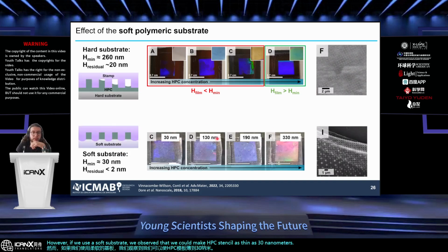And the reason that we believe this is possible is that with a soft substrate, I could press into the substrate and basically force the HPC to fill the stamp evenly. Another important benefit of this is that we would not have so much residual layer that we have to etch in the second step. So we only perform a 30-second UV ozone cleaning step, which is really making our life much easier, and we can avoid any kind of clean room steps. So everything is done benchtop, in a standard chemistry lab.